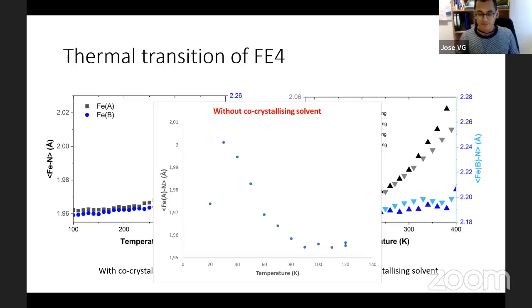This is because the thermal transition from low spin to high spin occurs when you increase the temperature. It's entropically driven, but here you are reducing the temperature and having a transition from low spin to high spin. This is an incomplete work.